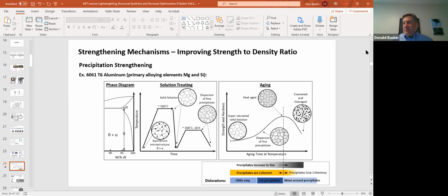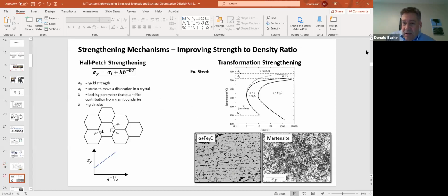We went back and worked with the supplier to minimize the amount of time the parts were in the oven and minimize the temperature of the aluminum, just to the point where you could begin to insert the electrical windings and wires and so forth. So we solved the problem, but the supplier really should have known better that there's this over-aging or over-precipitation problem that comes with aluminum. Unfortunately, they didn't. They knew more about electric motors, but they didn't know much about metallurgy. Okay.